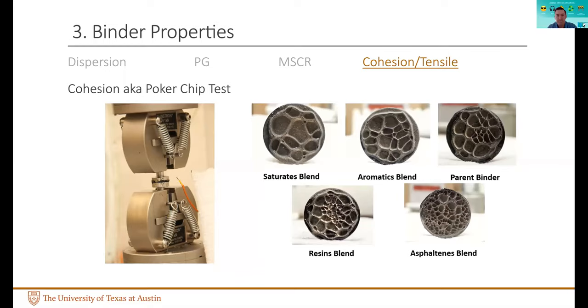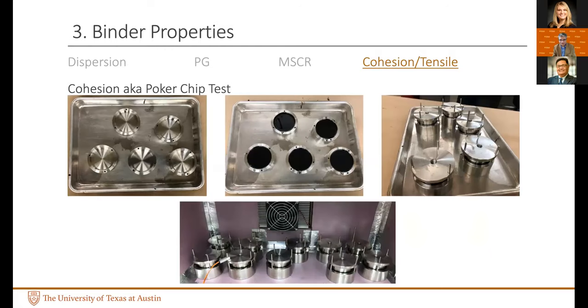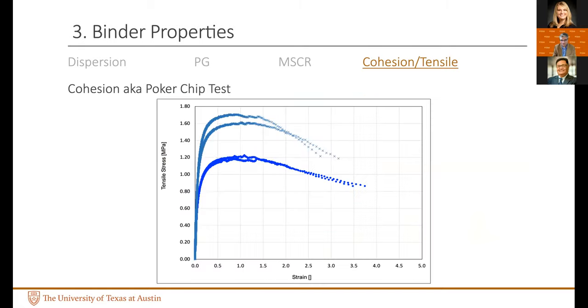So in any case, we have this test that actually is very sensitive to the chemical. This picture just shows the sensitivity of this method to pick up cavitation and failure and strength and ductility for different chemistries of asphalt binder. In a more recent incarnation of this test, we made it very user-friendly where you could run multiple tests on a typical Instron machine at 25 degrees Celsius. And we use this with our asphalt binders.